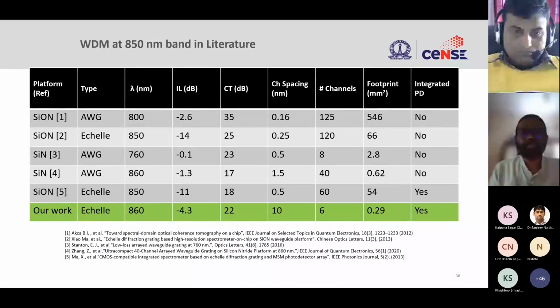And this is just to show how we compare with the rest of the demonstrations. One important thing to note is we have about 6 channels with 10 nanometer spacing. It is a very small device. You're talking about 0.3 millimeter square. When you talk about spectrometers, they are very large. So here I'm telling you that it is less than half a millimeter square. The device is as small as that.